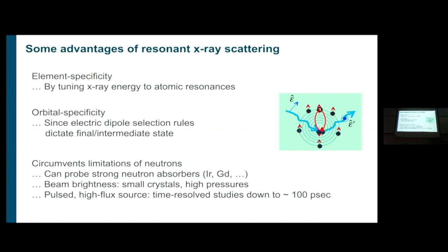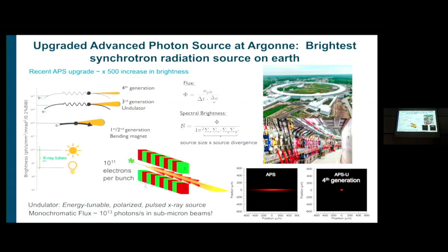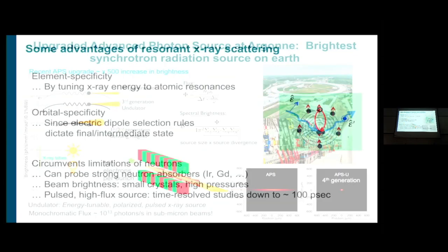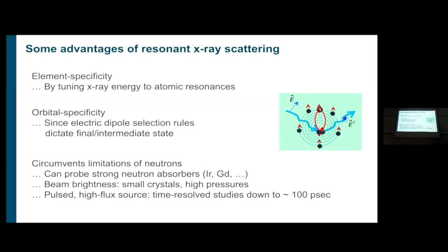Now, to wrap up, some advantages of resonant X-ray scattering, because we are tuning the X-ray energy. I forgot to mention that these undulators produce not very monochromatic X-rays. They are about 0.1% bandwidth of the energy. So if you have kilovolt X-rays, maybe 10 kilovolts, it's maybe a few hundred eV. You can scan the gap between these magnetic arrays, so you control the magnitude of the magnetic field, and then the energy of these X-rays can be tunable. And then you use a crystal monochromator to actually define the energy to a very high precision.